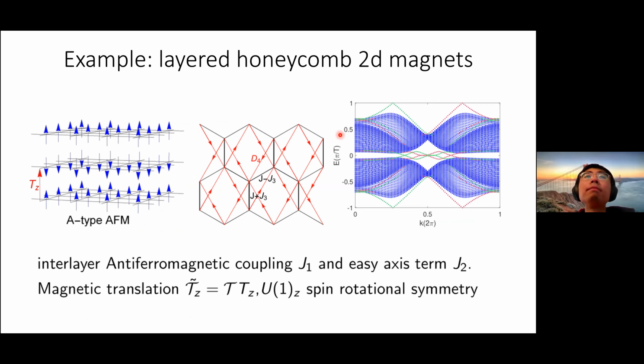Another example is related to the 2-dimensional magnet, for example chromium triiodide, which has been studied extensively recently. In chromium triiodide, if the number of layers is small, what people have figured out is that although each layer is ferromagnetic, between different layers there is antiferromagnetic order when the number of layers is small. In this case, we can show that we can drive the system with periodic light and again get this intrinsically non-trivial topology in the Floquet system. In this case, instead of having a chiral edge state, we have a helical edge state in the system.